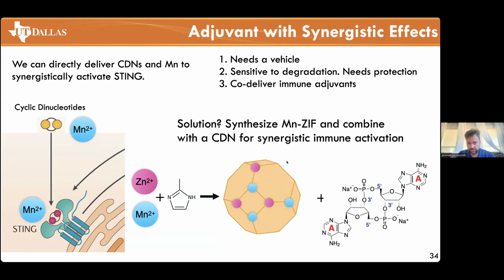And so we used this concept of ZIF-8, except we substituted about 50% of the zinc for manganese, and we loaded it all together. But just to further enhance it, we use this cyclic dinucleotide, CDN, and this cyclic dinucleotide also enhances or activates STING. So if the manganese weren't enough, we could also use CDN. We can see how they synergize, which they should, and we should be able to get a good response.